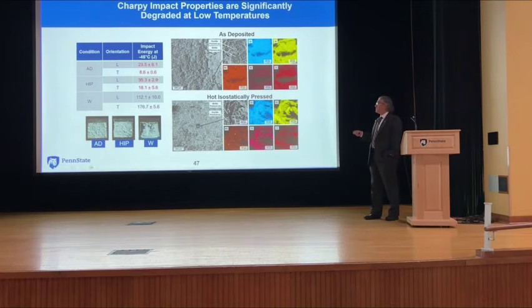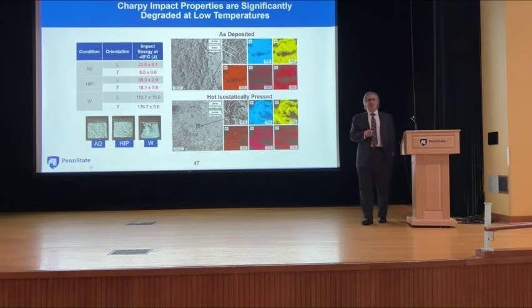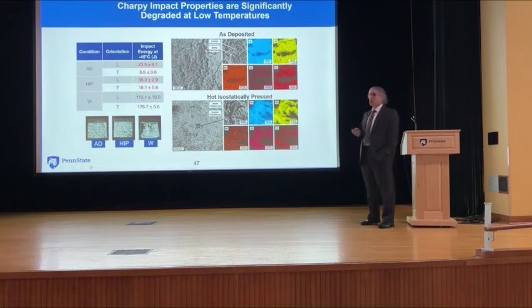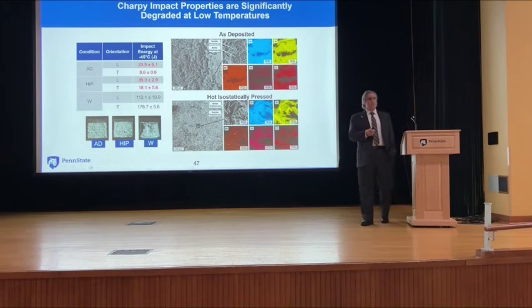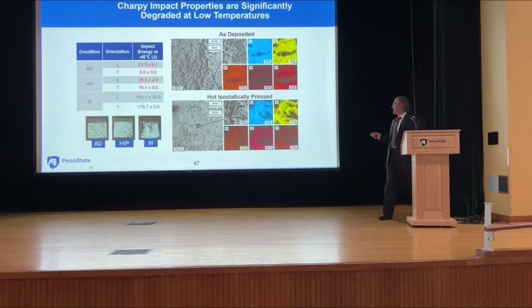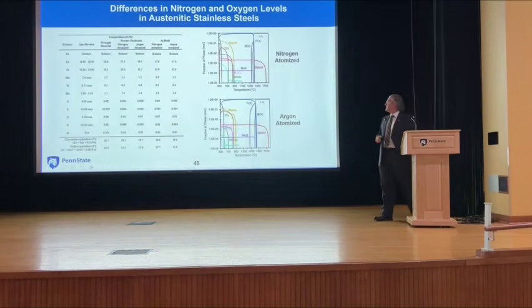Red is bad. So a wrought material is usually about 100 joules at a negative 45 degrees C impact energy, Charpy impact test. We were breaking them at like 8, 20. So the oil and gas industry says no way to using these because of that. Now, why is that? So a lot of it has to do with the size and shape of the ferrite and austenite phases, but a lot of it has to do with all of these inclusions sitting all over the place, going back to the role of interstitial gases in there.